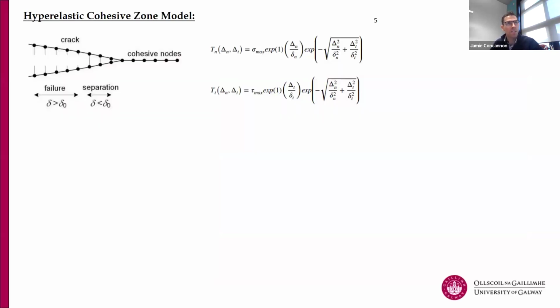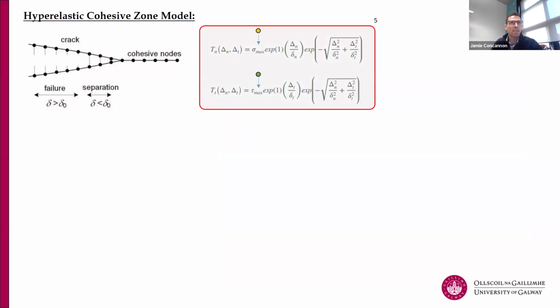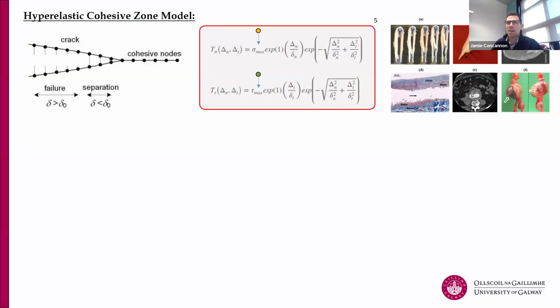So we said, great, we can do this. We came up with a hyperelastic cohesive zone model. And remember that green and yellow dot that I mentioned earlier, this exactly sits in here. This gives us the interface strength in mode 1, which is normal, and mode 2, which is shear. They sit into these equations, and they can degrade the elements, and this zip can open and the crack can form in a cohesive zone model. And we did this, and this is the type of behavior that you see when you subject arteries to loads when they burst and rupture.